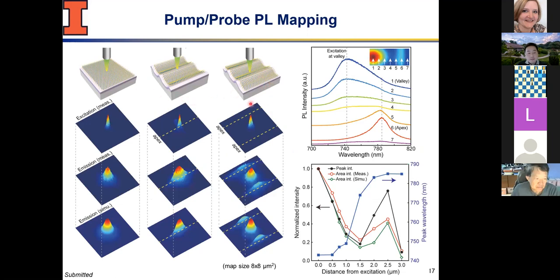So here is the experiment. It's a very simple experiment. I have a flat sample, I shine a laser. That's my excitation beam. It's circular. This is my emission beam. Not surprisingly, it's circular, but there's diffusion. So you can measure the radius of that to talk about exciton diffusion as a function of power, for example. People have done that. You can use that to calculate the diffusion coefficient, for example.